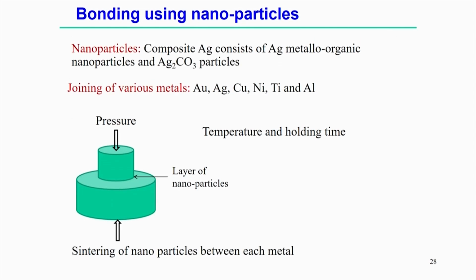Here, for the nanoparticles, we generally use a composite silver consisting of silver metallo-organic nanoparticles and Ag2CO3 particles, and using these particles it is possible to join various materials like gold, silver, copper, nickel, titanium and aluminum. It is possible to put a layer of the nanoparticles between the two samples, apply some pressure, and if needed apply some temperature also and hold for a certain time. Then these two samples can be joined by making the bond using the nanoparticles.